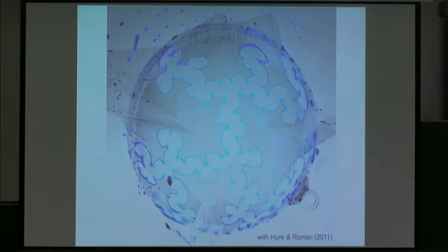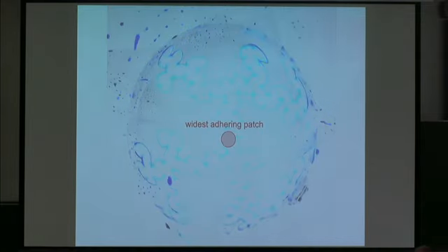So all this region here is a contact region between the sphere and the sheet, and apart from this region, the sheet is not in contact with the sphere. It's kind of messy, but what you can define in any case is a typical width of this region. So you can try to find... well, if I had a very small patch smaller than this region, I would be able to stick it on the sphere without making any wavy, any funny shape. But if I have something larger, I start making this wavy shape.